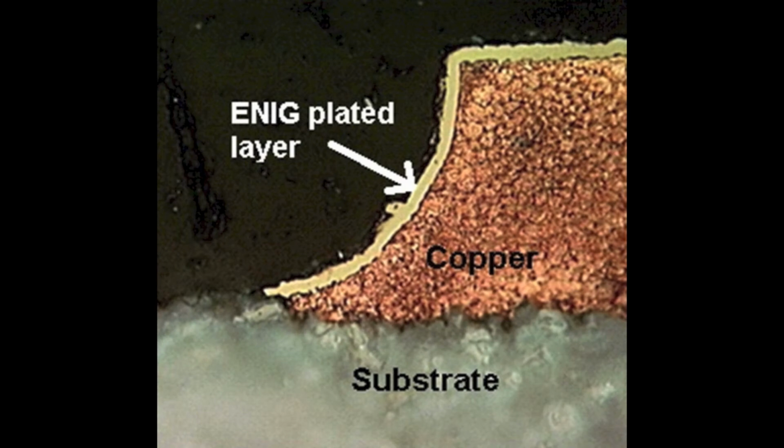As an example, to the left of that is a microsection of an actual circuit, taken of the signal conductor on the left-hand side. You can see the left-hand side of that signal conductor is obviously not perpendicular. It's somewhat trapezoidal, or even has an arc to it somewhat. Also on there I've noted the ENIG plating, and the ENIG plating here is really showing mostly nickel. The nickel is extremely thick compared to the gold. The gold is so thin you can't even see it.